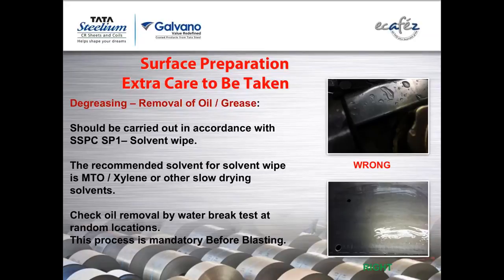Now, one more thing to note here is usually people will cut a carbide or old paint can and try to put the thinner in that. Then they will have one cloth rag which they will dip in, clean, again dip into the same, clean, again dip into the same. Naturally, you will be contaminating that solvent with oil, and probably you will end up putting that oil onto surfaces where there was no oil earlier. So they have to take it in a bottle, puncture the bottle lid, and pour it onto the cloth and then wipe. Another thing is they have to apply with one cloth and wipe it with a dry cloth. That will serve the purpose better.